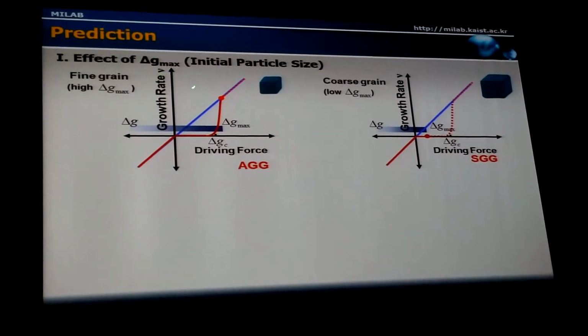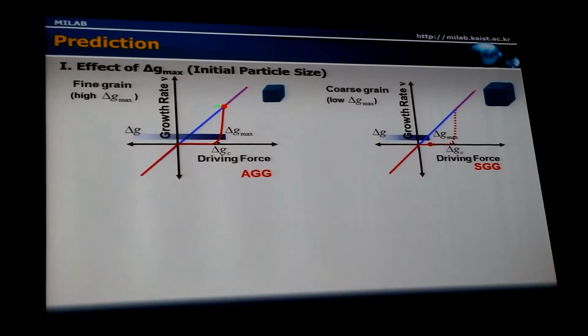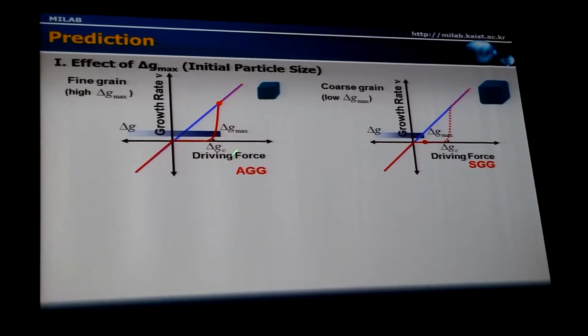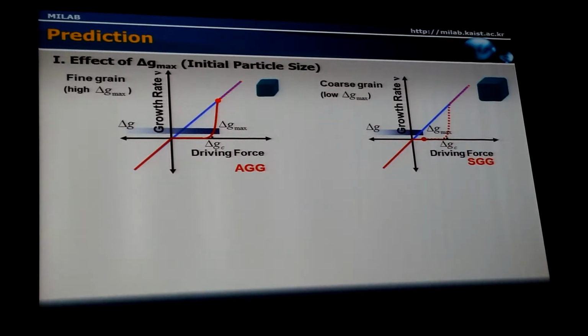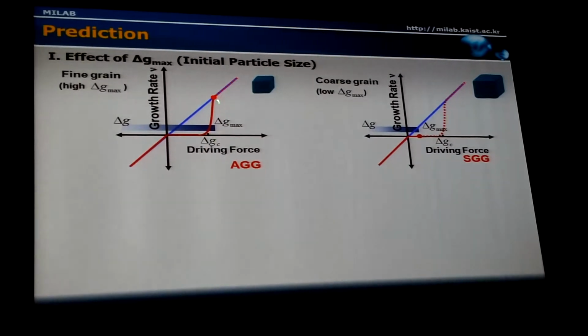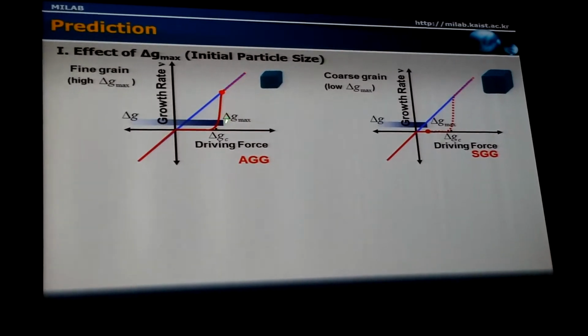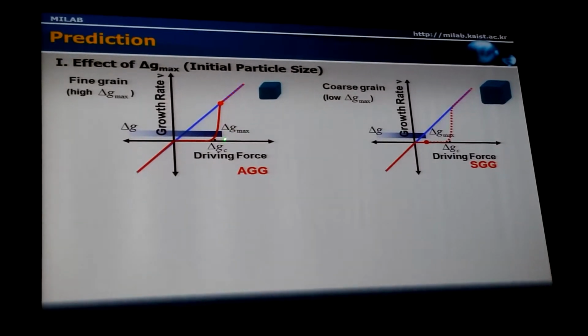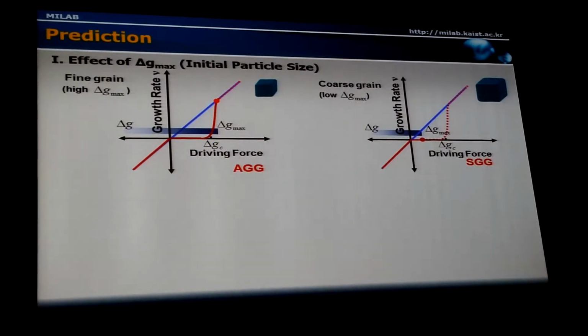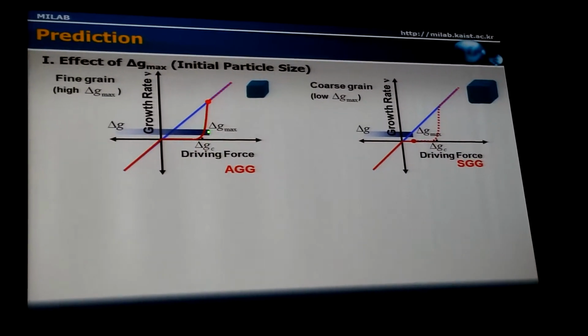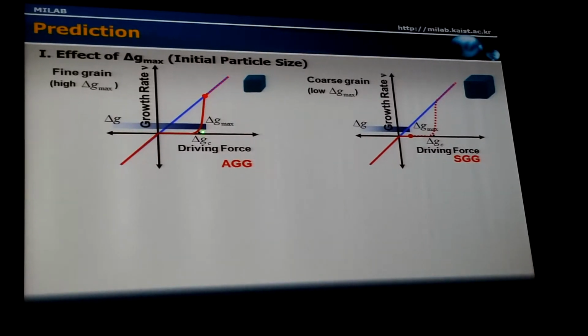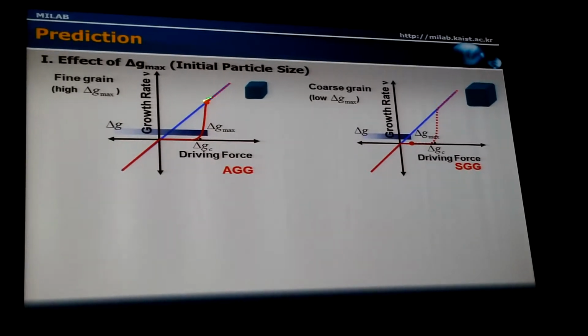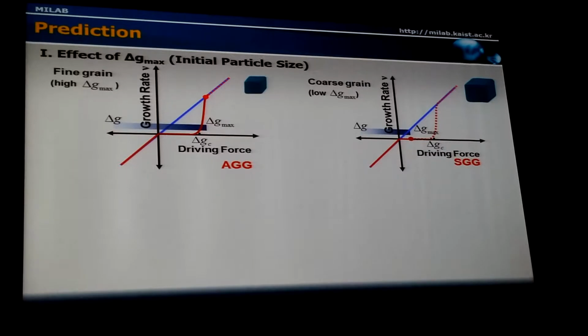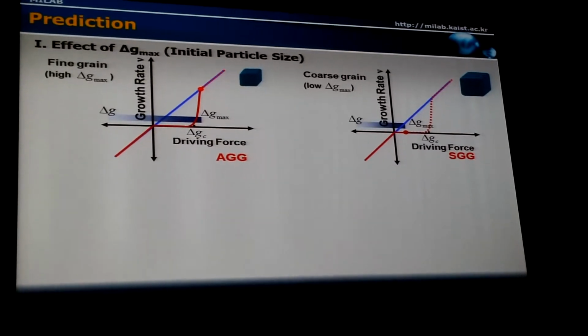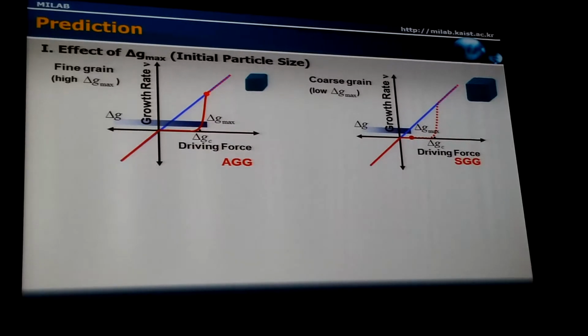For example, in the case of initial particle size, consider we have two different initial particle sizes, fine and coarse, but the grain shape is the same. In the case of fine grains, the maximum driving force is high, and it can be comparable with the critical driving force. In that case, only a small number of grains whose driving force is larger than the critical value will grow appreciably along this line, and the rest of the grains will remain unchanged in their size. That means abnormal grains form. A small number of abnormal grains will form.